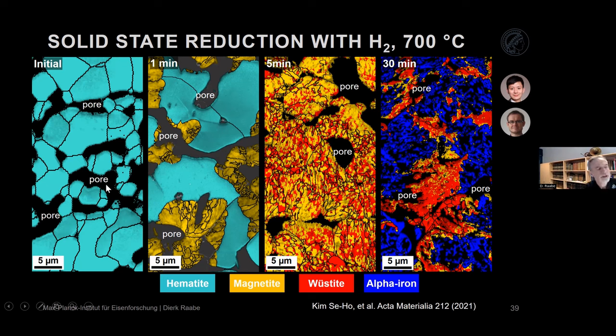So here's a snapshot of the structure through the reduction kinetics. You start from the left-hand side, and the hematite porous structure goes through the nucleation and growth of the magnetite, which is not so complicated to understand. Then you have this phase transformation from magnetite to wüstite, which is a very complicated kind of structural spinodal decomposition phase transformation, and then you form the iron. So these crystallographic features alone are really interesting and not yet very well understood.